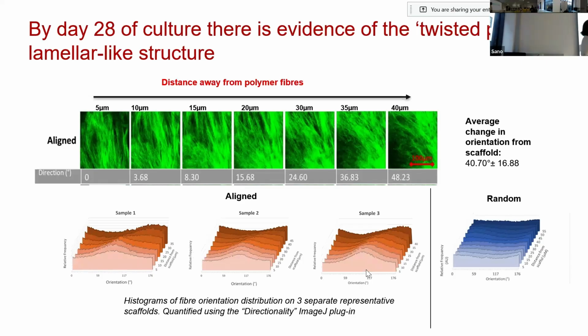So what you see here is this nice alignment, but we're already seeing a change in orientation as we come away from the original fibers. And if we measure this, we can see a peak of orientation which shifts as we go through the samples. If it was just one of those other scaffolds I showed you, that wouldn't have any orientation. So it really is the biomaterial that's allowing this orientation to occur.